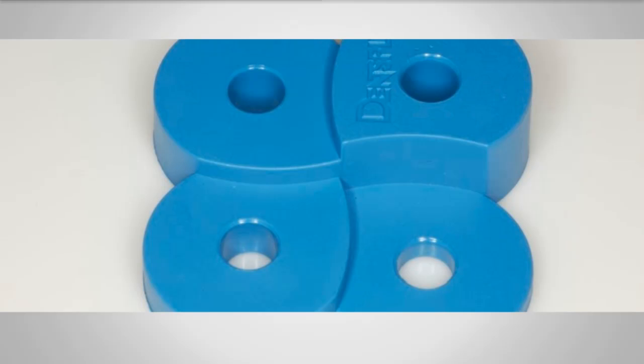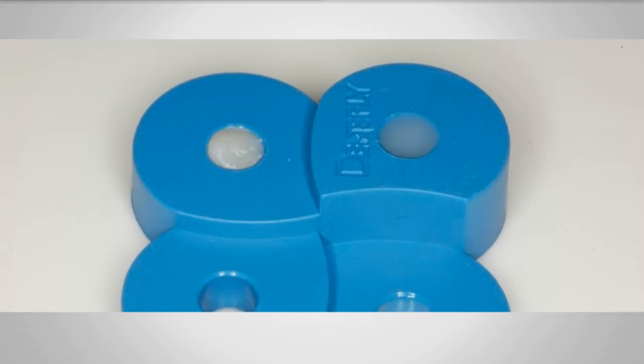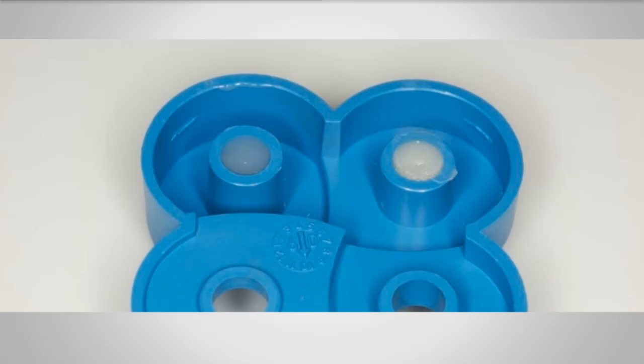Now, to test this, what I did was I was given this little piece of plastic with an 8 millimeter, a 6 millimeter, a 4 millimeter, and a 2 millimeter little step within it. And I filled the 8 millimeter step with SDR, which, as you'll see, is a little bit greyish looking material, and that's because it's quite translucent, which allows you to cure in depth. And I filled the 6 millimeter just with a regular nanohybrid composite, and then I cured them both from the occlusal surface, from the top there, for 20 seconds with an LED light, and then turned it over.